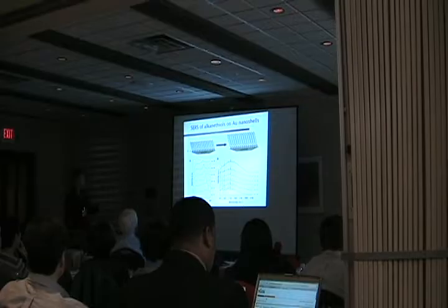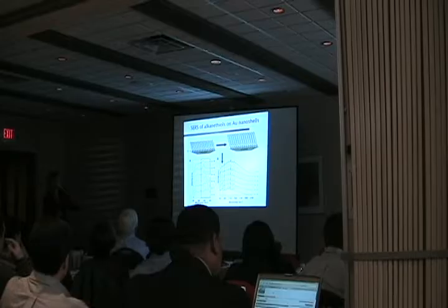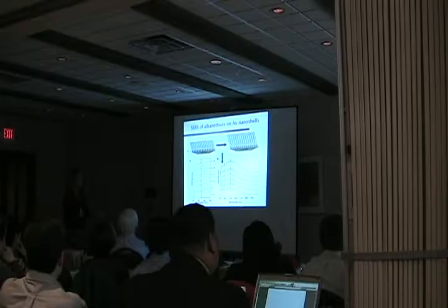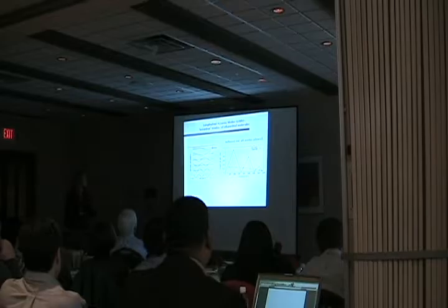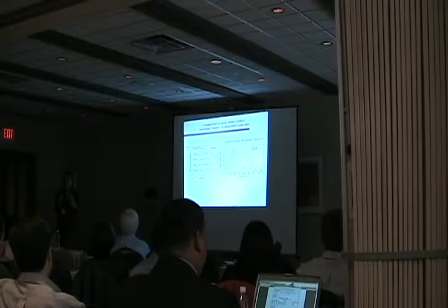Not only does it have a mass dependence, but we can also see these other interesting, almost overtone modes that begin to appear when we take the spectrum very carefully, all down in this low frequency region, very systematic and very reproducible. And it turns out that people have known for a long time that alkane chain molecules in solution all have accordion modes. They have longitudinal acoustic modes, and they have well-defined Raman frequencies that vary with the number of carbon atoms.